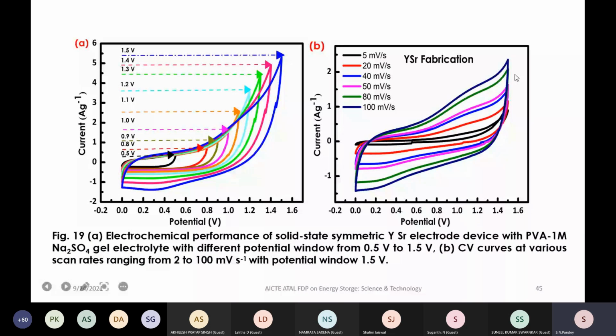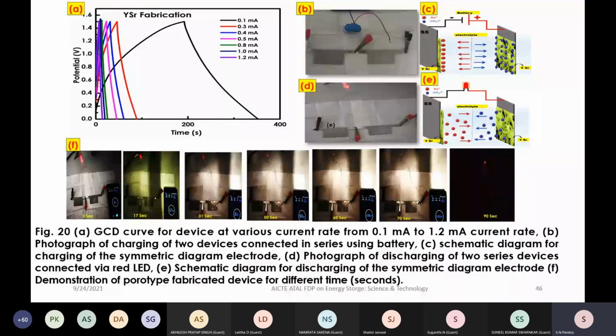And this B is the CV curve at different scan rates. If we change the scan rates and try to see what is going on, how the change is taking place, we have calculated the specific capacity. After that, the energy density and power density have also been calculated. But it is very interesting to see that the potential window is from 0 to 1.6. So 1.6 is going to be the potential window. This is the charge discharge of this fabricated YSR device, and then the galvanostatic charge discharge of the device at various current rates, from 0.1 milliampere to 1.2 milliampere, and it has the highest value at 0.1 milliampere.